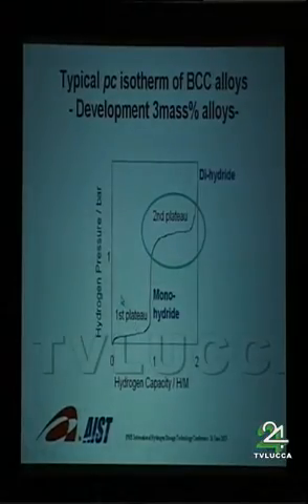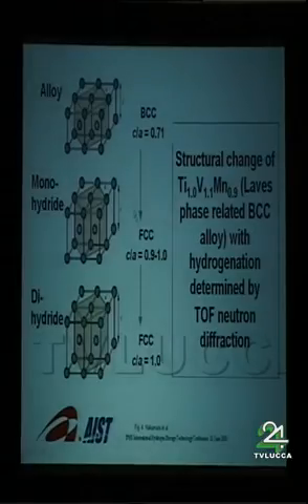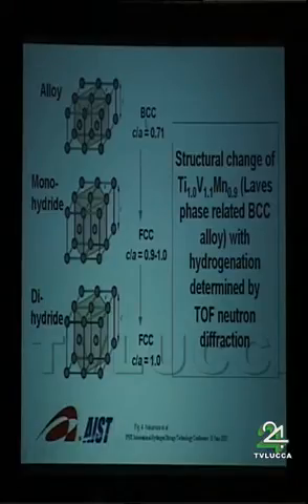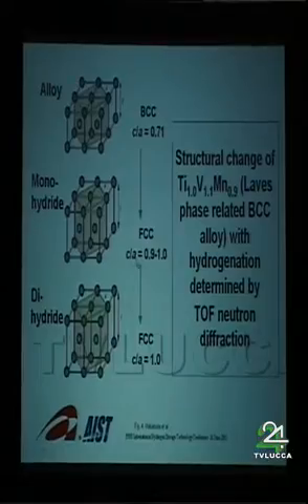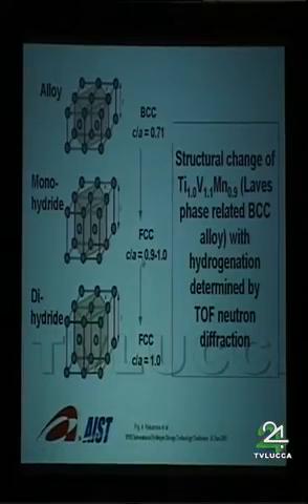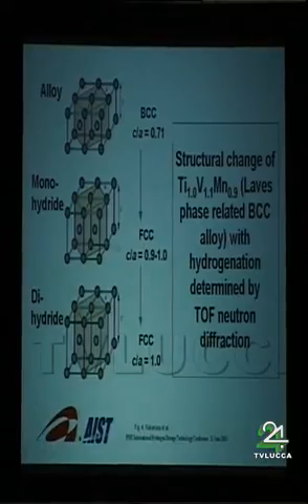And Daniel gave us some nice introduction to our Laves phase related BCC alloys. I just mentioned we use only the second plateau between monohydride and dihydride. Dihydride has a calcium fluoride, CaF2, type structure, but the crystal structure of monohydride is a serious problem. And we found in the titanium vanadium manganese alloy that it starts from a BCC structure, but in monohydride it has an FCC structure in the metallic sublattice. In some cases it is a distorted FCC, and in some cases a real FCC. It depends on the chemical composition.